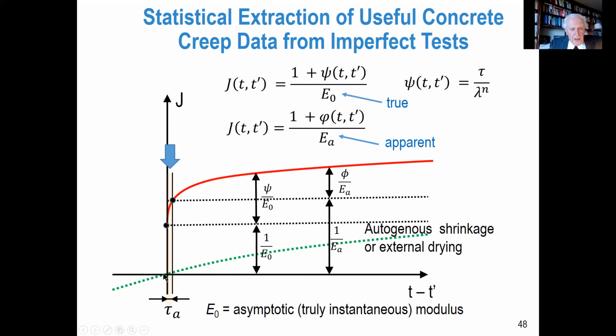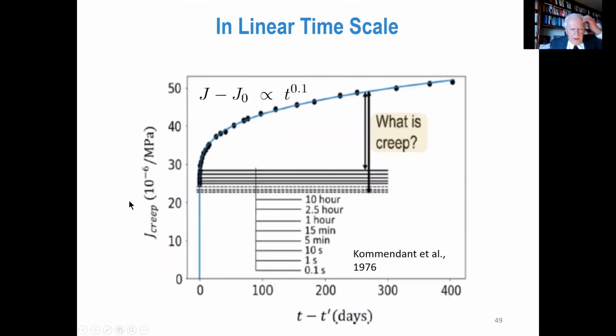But here in this range, autogenous shrinkage changes little. If drying started before, it will also change little. So only one phenomenon, which is hydration driving self-desiccation. So there must be self-similarity. This must follow a power law. So we can fit a power law to the data, which is shown here. We conclude about 0.1. These are typical data.